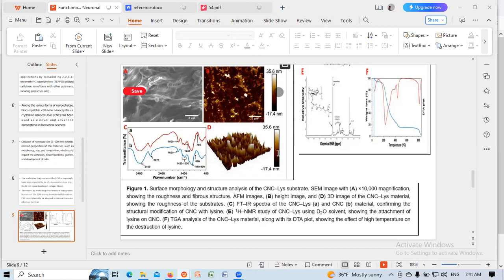The average roughness and root mean square average roughness were 6.16 and 8.96 nanometers respectively. In the FTIR analysis: 3400 per cm due to OH vibration and 2870 per cm CH stretching; 1300 to 1400 per cm may be the glycosidic bond; and in the anomeric peak region 900 to 1110, it may be the beta-glycosidic linkage of C-O-C glycosidic vibration.